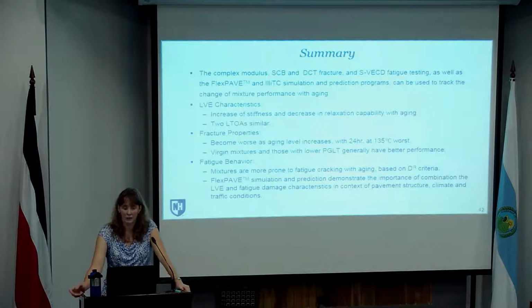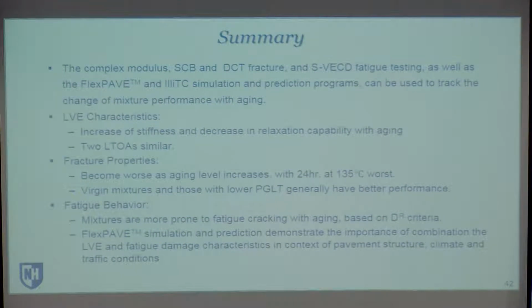In terms of the linear viscoelastic characteristics, as expected, we're seeing the increase in stiffness and decrease in relaxation capacity, and those two long-term aging conditions, the 12 days at 95 degrees C and 135 degrees C for 24 hours, are showing similar results in terms of the viscoelastic characterization. So for your mixture, if all you're caring about is that viscoelastic characterization, you can do the faster aging protocol. It's giving you the same results.